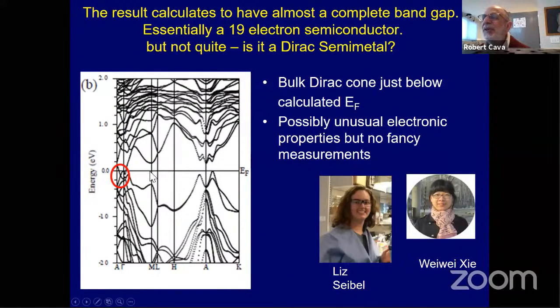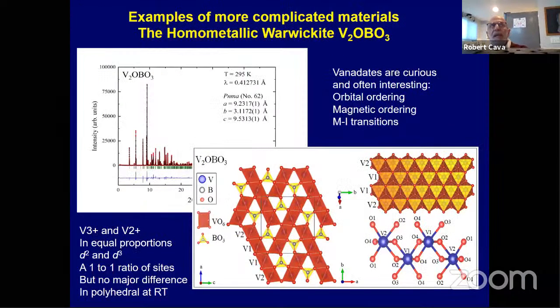Okay. And P.S. is another case of too many trees in the forest here, but this thing is mostly gapped, so it's mostly like an 19 electron semiconductor. But there's one little region in the Brillouin zone where if you calculate the band structure with spin-orbit coupling, you get a little crossing over here. So it's almost completely gapped, but not quite completely gapped. And if anybody ever cared to look at this thing, they might discover some interesting topological physics. And Liz and Wei figured this out.